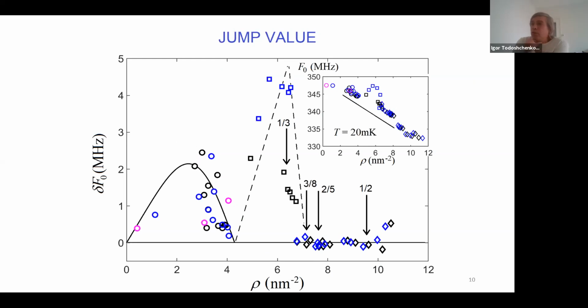This is the value of the jump at the transition, and this is at low coverages, and this is not a fit. This is a calculation, because once we know the critical parameters of this system from the phase diagram, we can simply calculate how much helium is near the ends and integrate the effective mass and obtain this curve. So it's not a fit. It's a calculation with no fitting parameters.